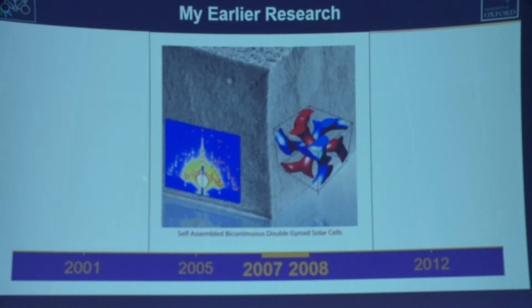Following this notion of needing this structure, this bulk heterojunction or mesoporous structure from the titania, I did quite a lot of work with my group structuring oxides in a more controlled way. This is an example in collaboration with a colleague called Uli Wiesner from Cornell University, where we made a double gyroid template from block copolymers. These are self-assembled molecules that make this structured template. We could then infiltrate it with a metal oxide precursor and form a porous double gyroid structured titania.